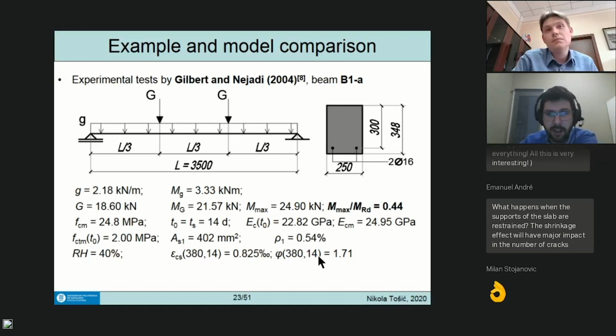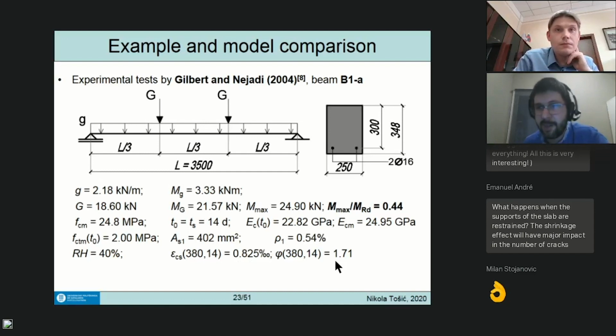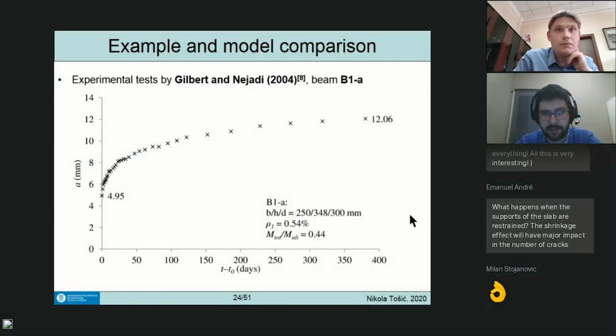Try to model creep and shrinkage with these inputs, with 40% humidity and these strengths, and at the same time get such a high shrinkage strain and such a low creep coefficient. It's a bit a strange combination, but just goes to show the scatter of the results of these models. You would expect a concrete having such a high shrinkage strain to have a much higher creep strain, but that's just the result.